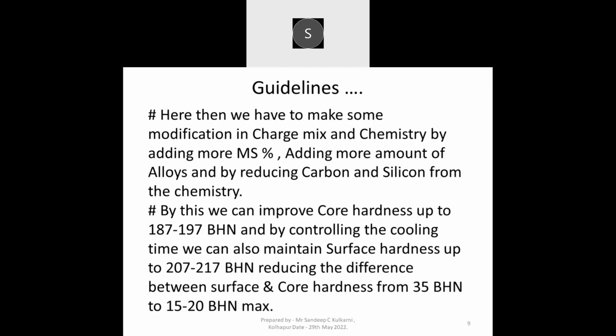So, by adding MS, by controlling the alloys and the cooling rate, we can reduce that gap between core hardness and surface hardness. By maintaining proper chemistry and proper charge mix, we can get good surface hardness as well as good core hardness, which will reduce your issues like porosity, shrinkage or open grain structure.